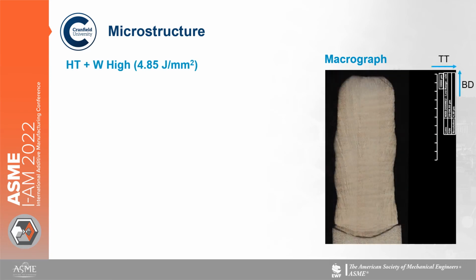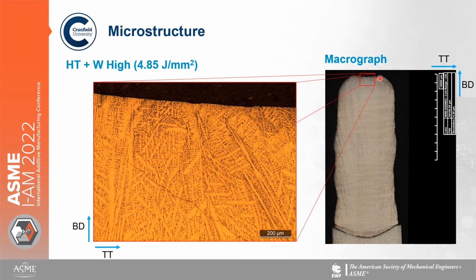So here's the microstructure of our highest energy peened material. This is the sample which had the highest input energy into it while working, so that's the slowest peening tool travel speed. And again, you can see our columnar grain structure. But when we take a closer look at the top, where you can see the indentation from the peening tool, the dendritic structure is much more disrupted than it was in the non-worked material.